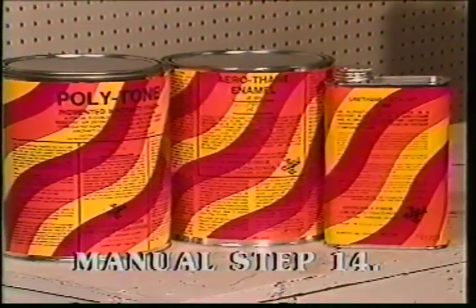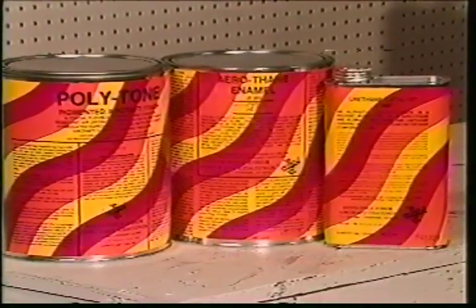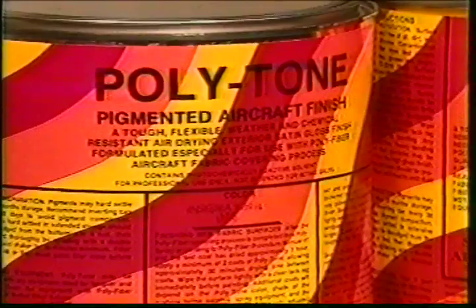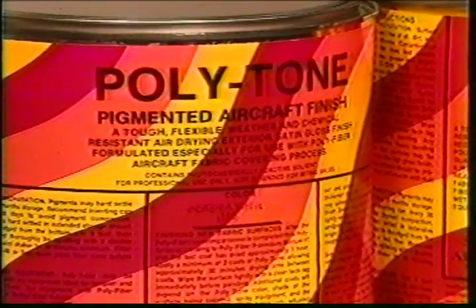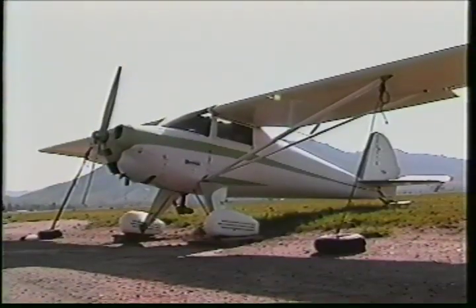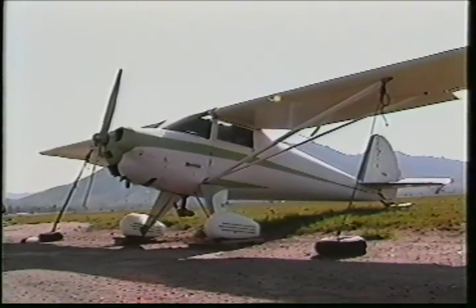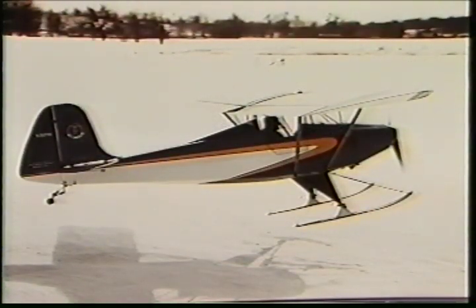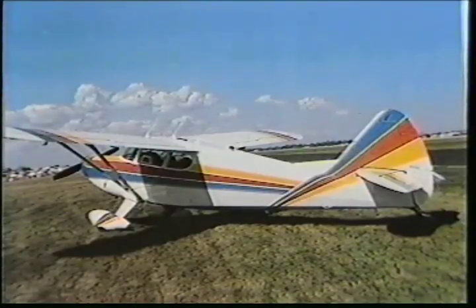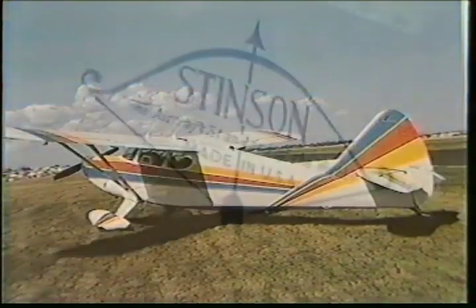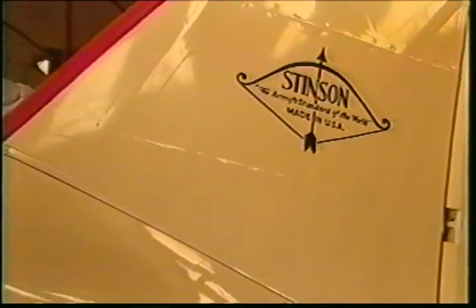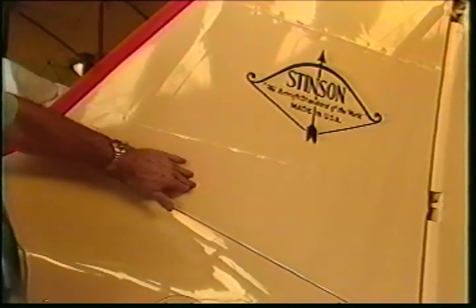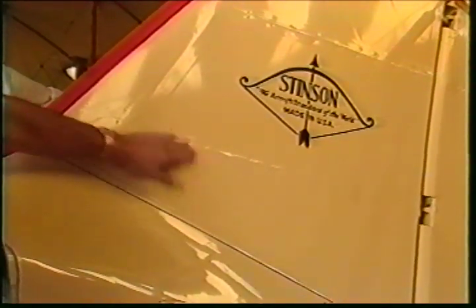After the final coat of poly spray has dried about an hour, the wing is ready for step 14, the pigmented finish. In this case, we are going to use polytone rather than aerothane, an optional high-gloss, very durable, flexible polyurethane enamel. Polytone is a one-part, fast-drying finish formulated to be durable in hot, sunny climates and remain flexible in very cold climates. It is easy to repair and hide hanger rash and other damage. It may be rubbed with a compound and waxed to produce a gloss equal to any other one-part finish. Polytone is also recommended for metal components when the fabric is finished with polytone to assure a good color match. It is used on metal only over clean, scuff-sanded epoxy primer to assure a good bond.